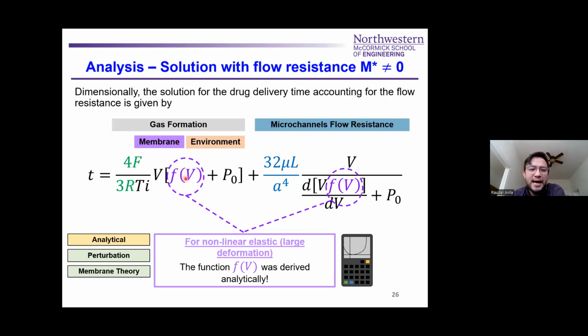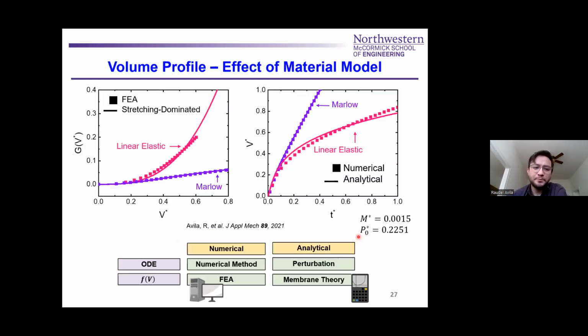So now we have found a way to model our function f(V) if we have some generalized hyperelastic law, or if you have some experimental data for your particular membrane that you're interested in. So you can solve this equation using a calculator now instead. And here I just want to highlight the implications of selecting a correct material model, because here you have pressure versus volume, and you're quantifying the amount of pressure it takes, or the volume that's going to deform at a given pressure.